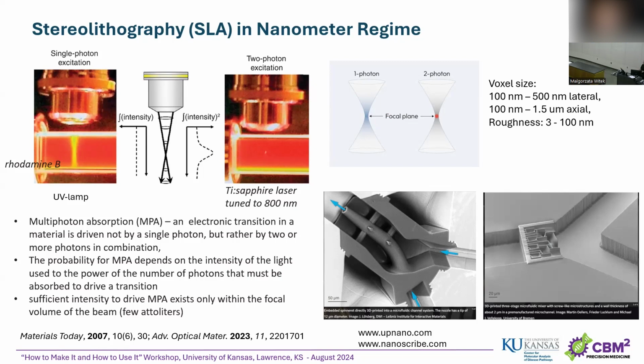If you use 2-photon with fast lasers, you really make sure that the maximum intensity is achieved only at the focal plane, because it's based on probability that you need at least 2 photons to polymerize your polymer, your resin. It is probability, basically.